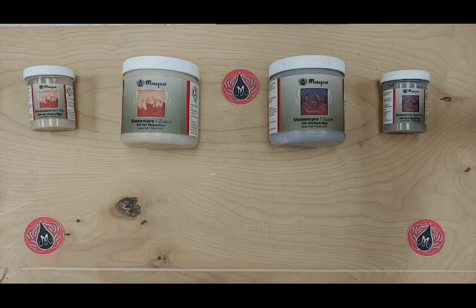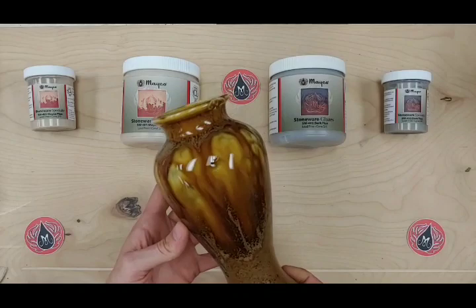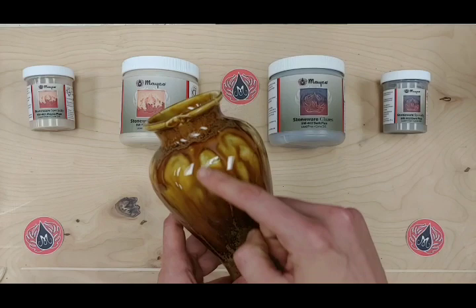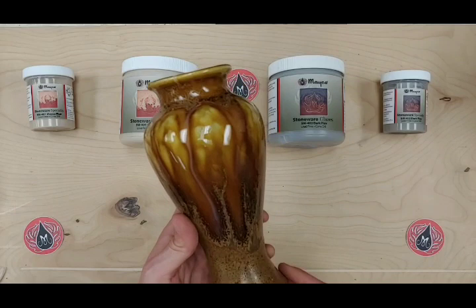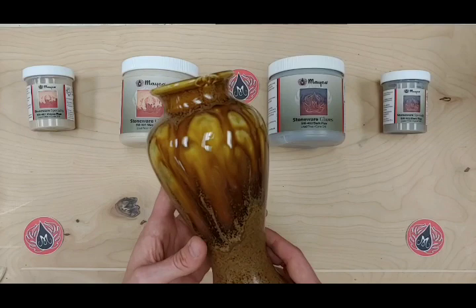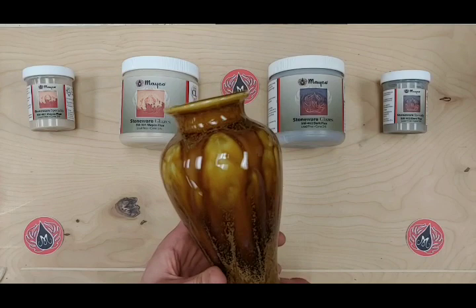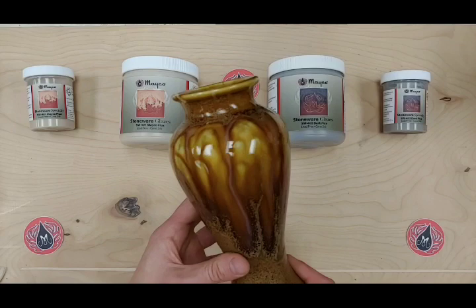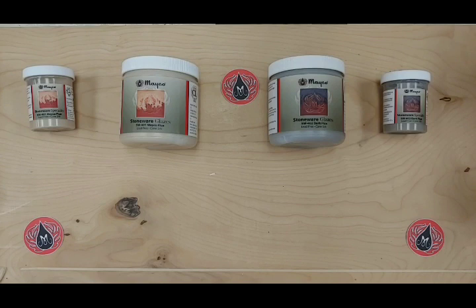Here's another example of Flux on Tea Dust. Tea Dust is a glaze that reacts a little bit more and does produce some mobility. On this specific piece, the Flux was banded on or trailed on with a slip trailer — so it was a pretty heavy application. You can see how it moved down almost past halfway down the ware. This was light Flux used on this piece, and there are some spots of Stroke and Coat as well. Overall, I do find that light Flux has a bit more mobility than dark Flux. If you want to produce the same amount of mobility with dark Flux, I'd recommend applying it a little bit heavier or pairing it with a glaze that has a lot of mobility.